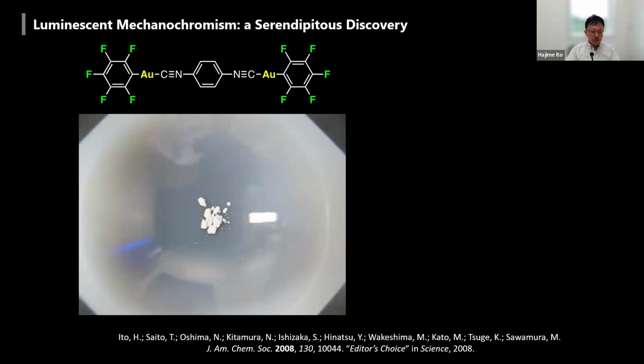This compound is very stable. We can keep this compound on the bench for 2 or 3 months without any chemical degradation. Instead of catalytic activity, we found something very interesting: this compound can show very interesting photoluminescence properties.